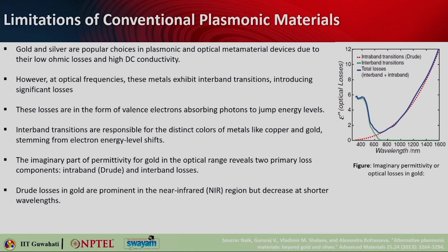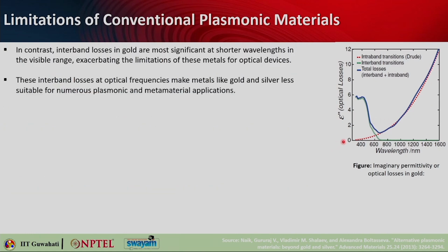Okay? And in this particular diagram you can see that the imaginary part of the permittivity is being plotted, and the finely dotted one shows the interband transition, and this one shows the intraband transition. And what you can see is that the Drude losses, the intraband transitions, are more prominent in the near infrared regime, but they decrease at shorter wavelength, and at shorter wavelength you can see that interband transitions actually dominate and they become the main reason for optical losses.